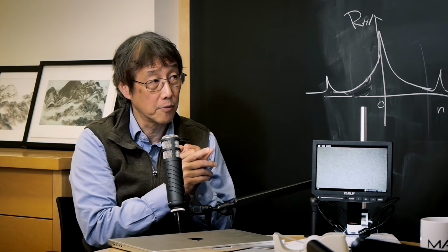But it seems like it's going much beyond that. It is still not completely resolved why twisted graphene becomes a superconductor. We know that density of states plays a role. It's a relatively low temperature, about 1 Kelvin, or in special cases a few Kelvin, but it's not really high temperature. But the reason that superconductivity in twisted graphene or twisted systems can be important is that it provides a model physics system one can study. Like the AMO system, for example, where the model Hamiltonian lets you look at the right physics, this twistronics or twisted system provides an engineerable system where you can test out some of the physics.